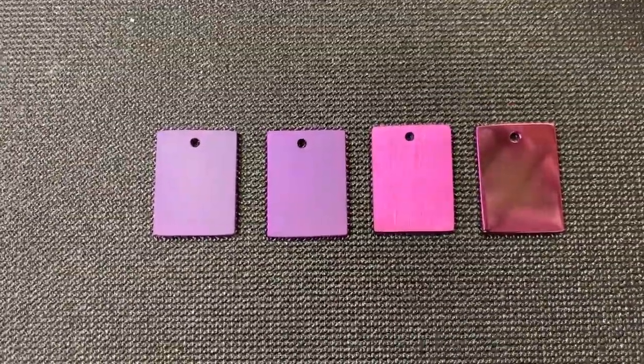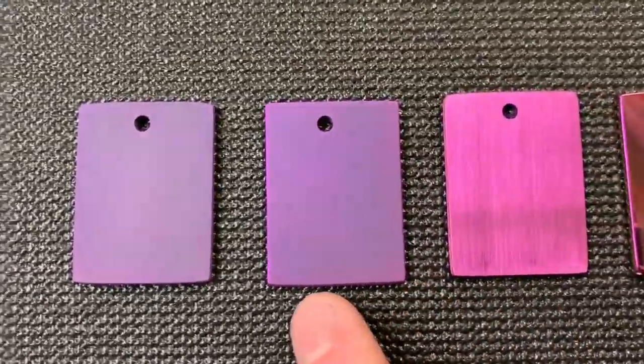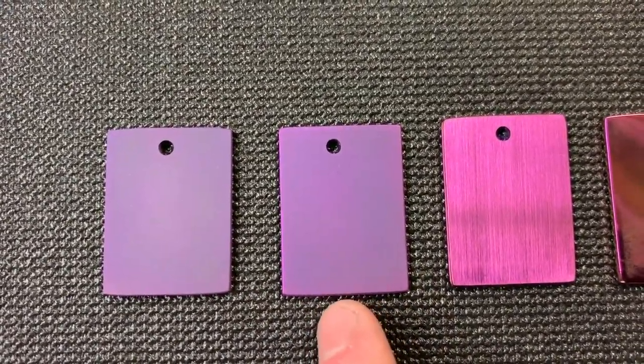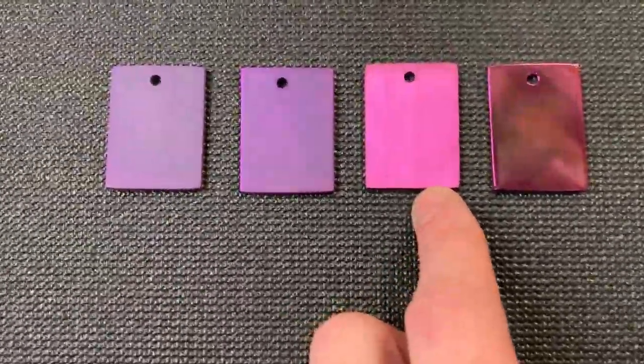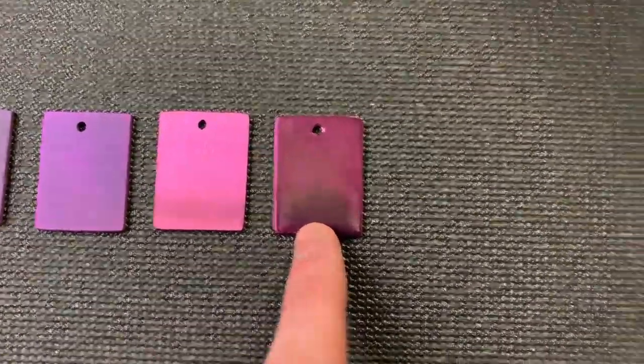This is what I like to call ultraviolet — about 75 volts. Zooming in: on our blasted one, that's purple. On our tumbled one we have a little more vibrant edges, a little bit brighter purple. Over into the satin, that is pink — right on the borderline of pink and purple — and then the polished one also looks pink.